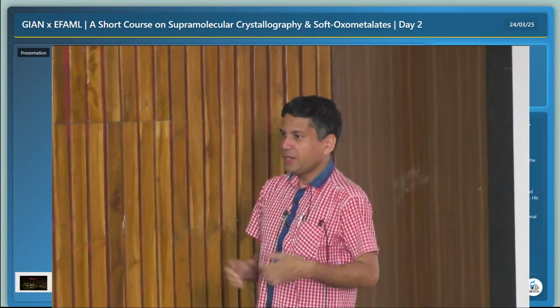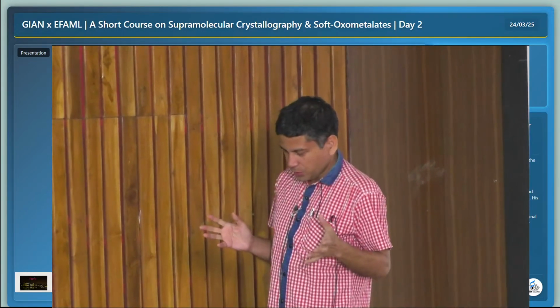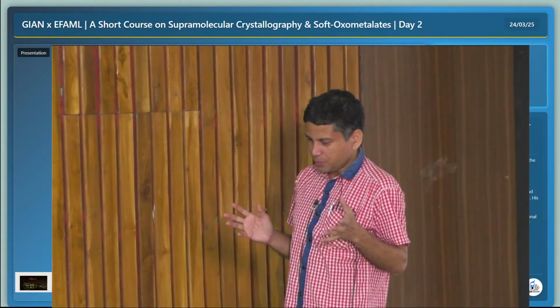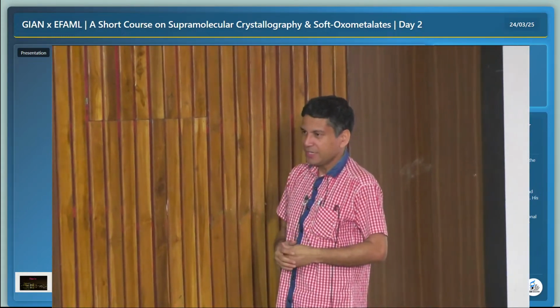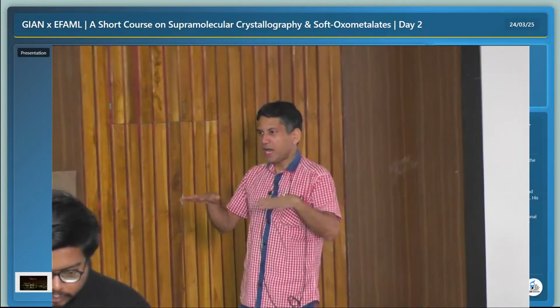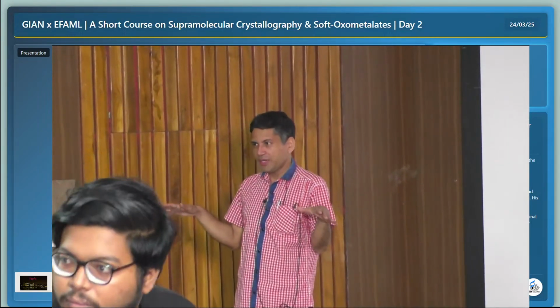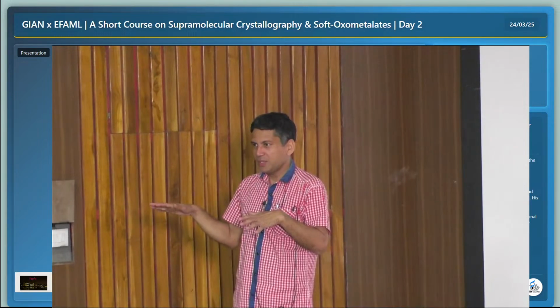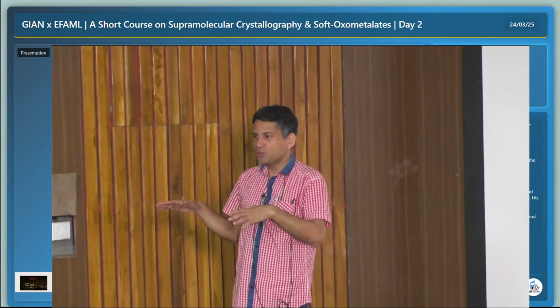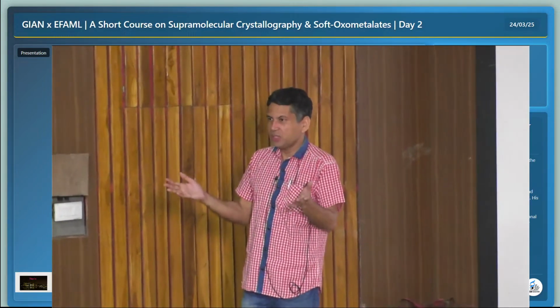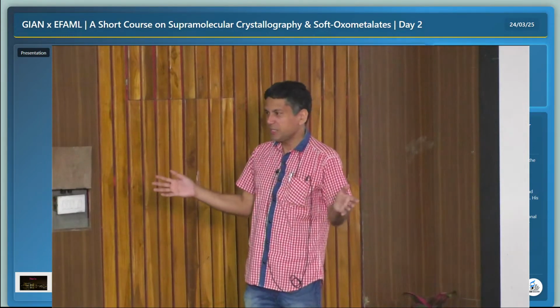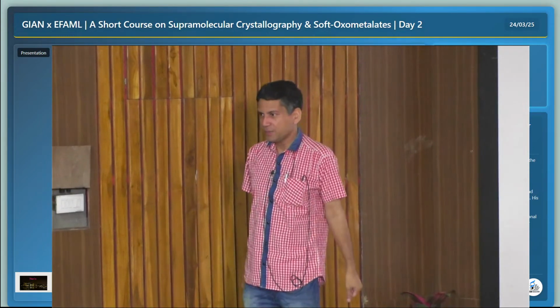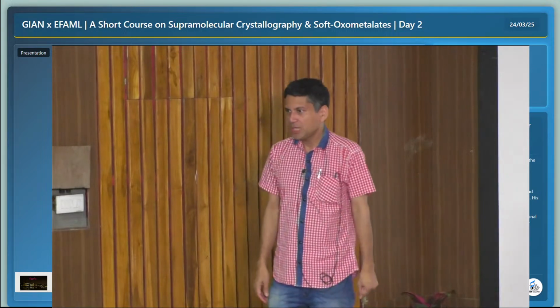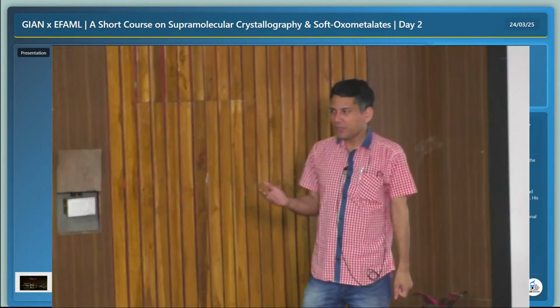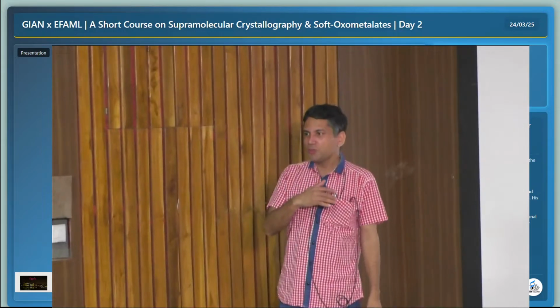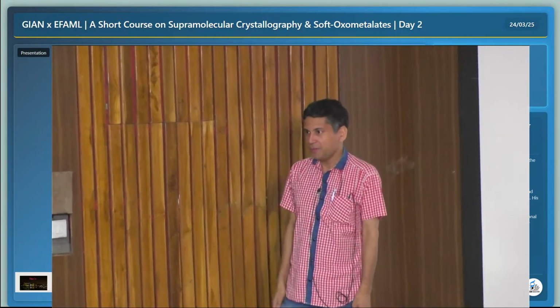Okay, thank you. And it's easy to separate the product from the reaction inside the gel, because the gel is very, very hydrophobic in nature. It's soluble in hexane and some hydrophobic solvents, and our product is not soluble in that. So you just use a different solvent system, very easy to separate the product and purify. And if you can separate the product, you can reuse the catalyst multiple times.